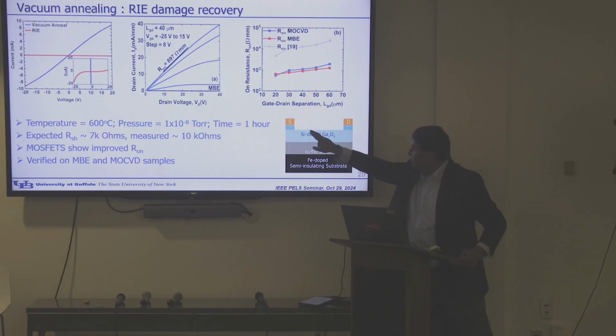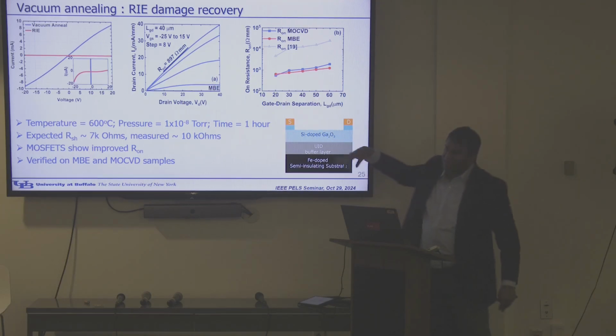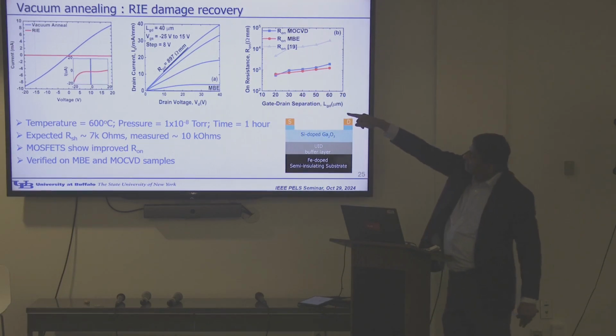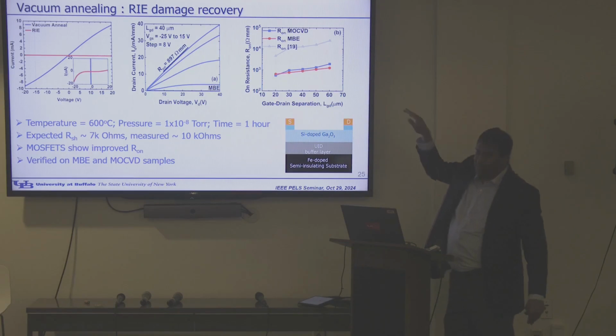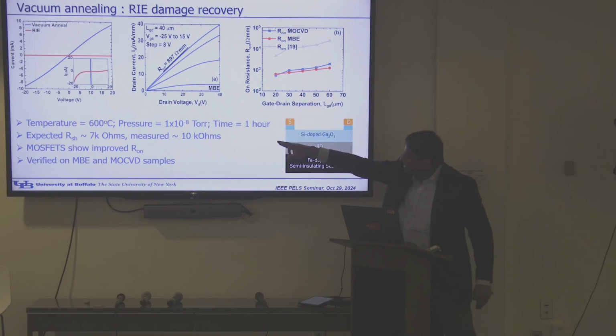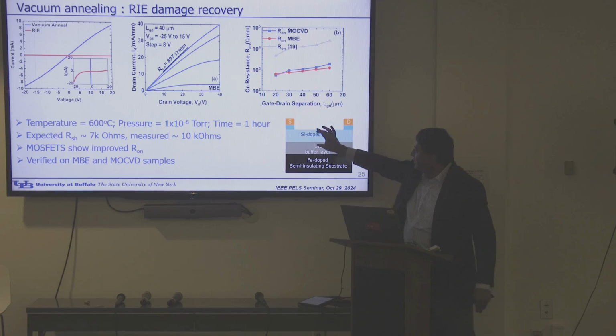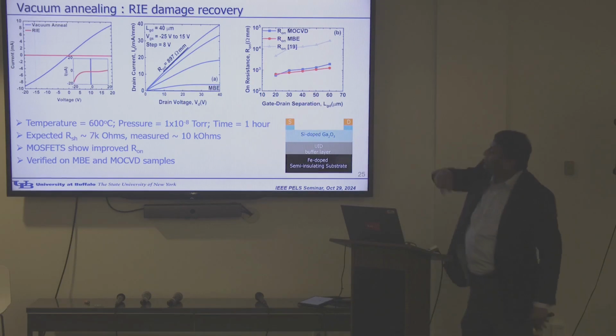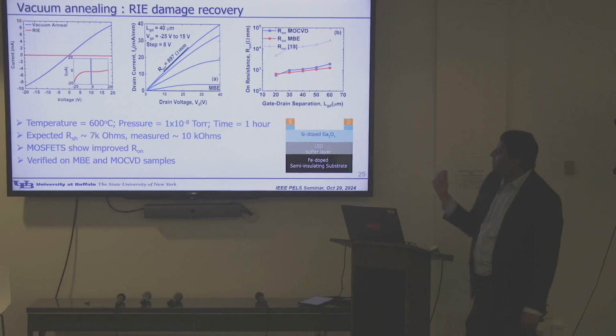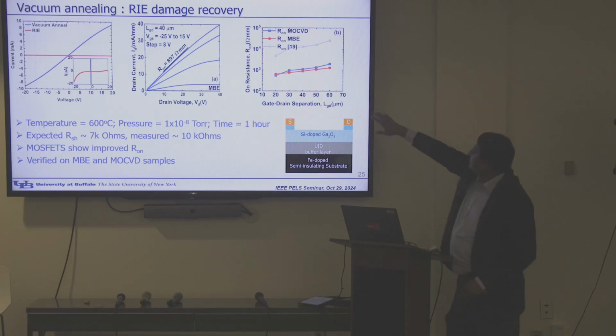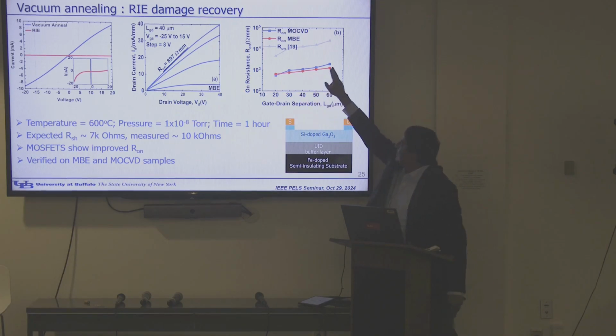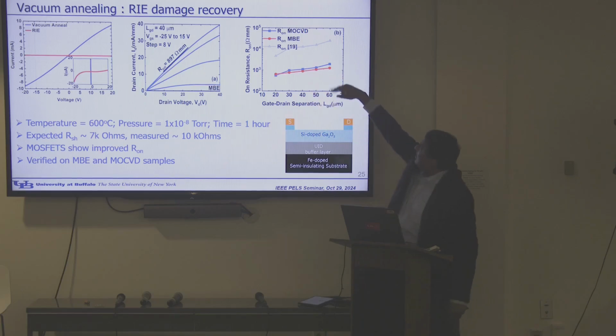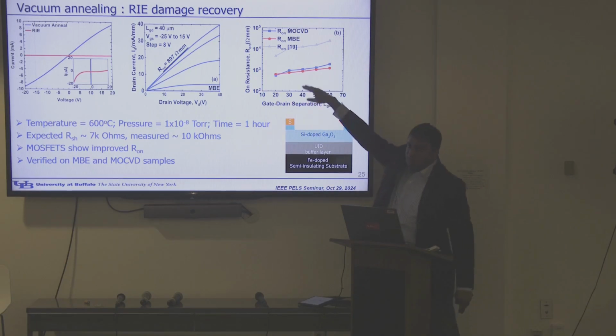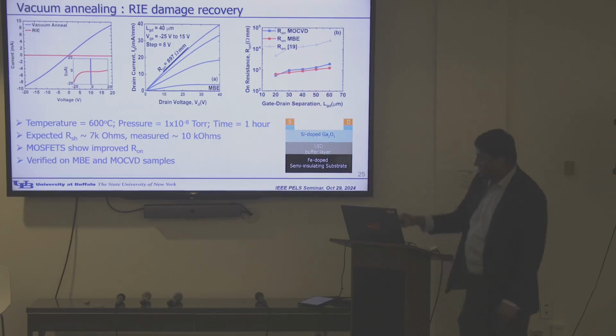The on resistance, you can see that what happens is the N plus layer, when you do RIE here, if you're not careful, you can damage this channel layer, increase the resistance. You can see on the red line there, microamps, because of RIE, the current has dropped. But you go back, you anneal the device in an ultra high vacuum, and then this recovers. You can see the blue line on the left, the currents have gone up. In the center figure, you can see the resistance has improved there. Now here you can see that these are two different sets. The previous generation, the gray triangles, and you can constantly see improvement in the breakdown voltage, resistance here.